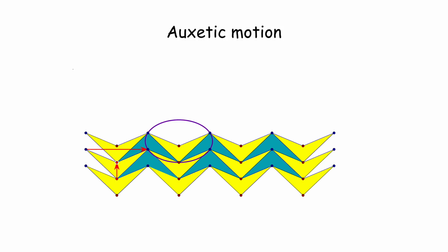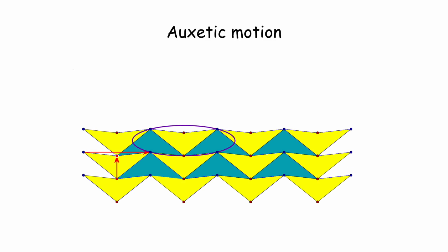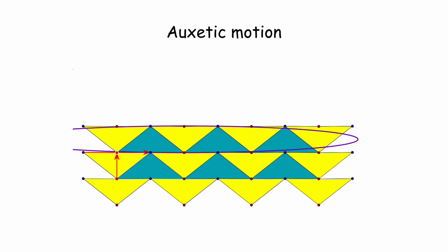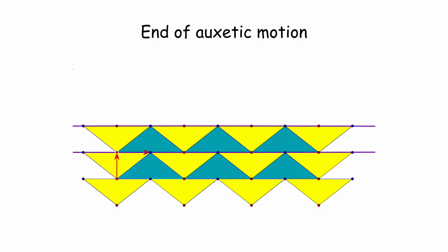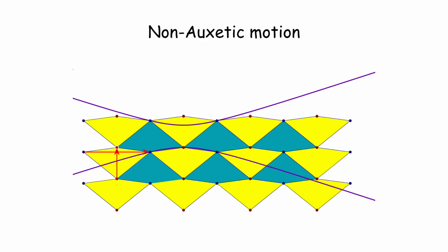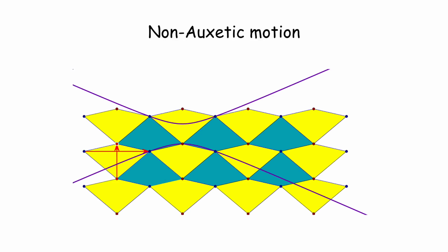I am auxetic, I'm expanding both vertically and horizontally until this is now a very elongated ellipse. And now the ellipse has degenerated into 2 lines, and this is the transition to the hyperbola. So now, although I'm still increasing in one direction laterally, I'm receding, so this is not auxetic anymore.